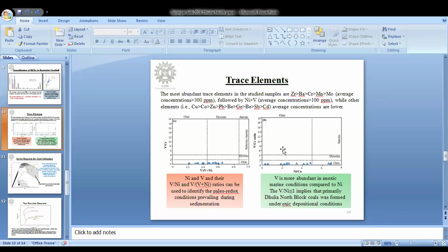And the two graphs which I have shown, we plotted again because we wanted to know the conditions under which this coal block was formed, so that we can exploit it in a very efficient manner. There are certain things to know, which is that vanadium is more abundant in anoxic marine conditions compared to nickel. And as you can see, the ratio of vanadium to nickel was less than 1, which implied that primarily these coal samples were formed under oxic depositional conditions. And further, we did some plots using nickel and vanadium concentrations. And from those also, we concluded that the paleoredox conditions prevailing during sedimentation were oxic, indicating that these coal blocks were formed under oxic conditions. This was the unanimous conclusion.